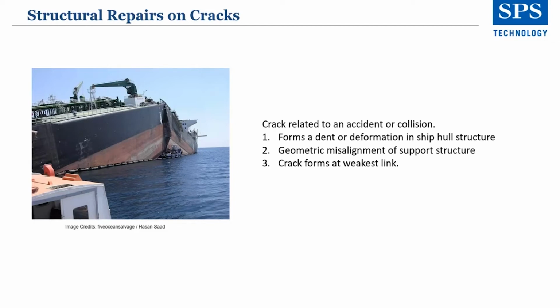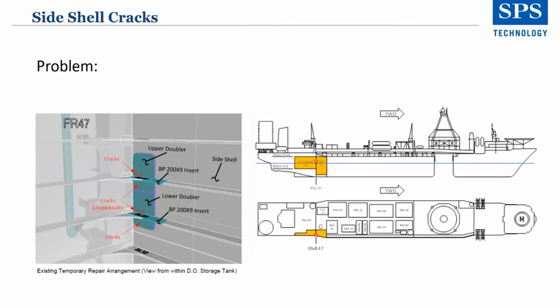But ships are complex and very large welded structures, and it's difficult to manufacture them without introducing some structural blind spots. There will be some sort of flaw, notch, discontinuity, or stress concentration. The normal procedure followed once cracks are detected during inspection is that they are gouged and rewelded, followed by non-destructive examination. Okay, so we're going on to the problem with side shell cracks as an example.